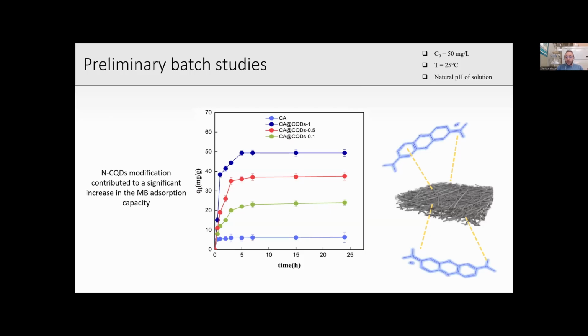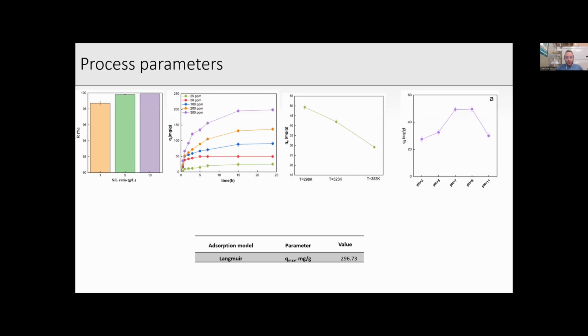The effect of the loading of nitrogen-doped carbon quantum dots was studied. It's possible to observe that just a small concentration, about 1%, is sufficient to obtain really great adsorption performances, and it was not possible to go over this concentration since the instability generated by the filler during the electrospinning process. Then, as usual, different process parameters were varied and tested to evaluate and study the adsorption performances of this new material, such as the solid-liquid ratio, the initial concentration, the temperature, the pH, the presence of salt as well.